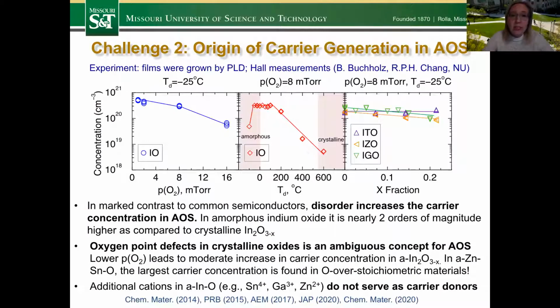Challenge number 2 is the actual origin of carrier generation in the amorphous oxide semiconductors. So I'm a theorist, but I will be talking a lot about experimental results of my collaborators. Here, these are experimental measurements, just Hall measurements of carrier concentration in indium oxide. And in the middle, you can see that this carrier concentration depends on the temperature of deposition. So essentially at high temperatures, when we deposit by pulsed laser deposition, we have crystalline films.